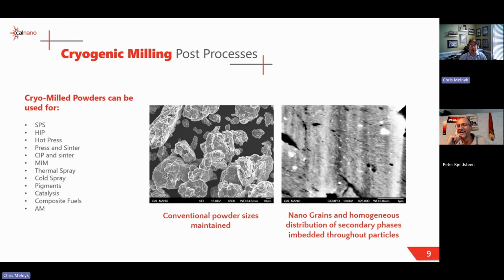Absolutely. So our smallest R&D scale, we can go down to 500 grams, but that's really on the low side. So our typical starting R&D run is 1 kg. And then we have various mills that go all the way up to about 50 times that. So the typical workhorse is probably in the 25 kg batch range.